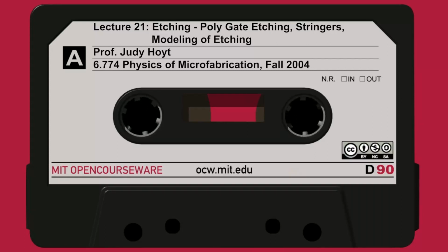After you pattern your photoresist and you develop it and you're ready to etch it, underneath you have 2 different types of layers. You need to etch a silicide layer in this example, which was pre-existing. As a uniform layer, it has to be etched, and then you need to stop on the silicon and then switch gases to etch the polysilicon underneath. Now this gets a little tricky. So you have 2 different etch gases. That doesn't sound too bad. You have an etch gas to etch the tungsten silicide, and another series of gases you use to etch the polysilicon. One problem, though, you can come across, for example, tungsten silicides may not be super pure. It may have some oxides incorporated into it.